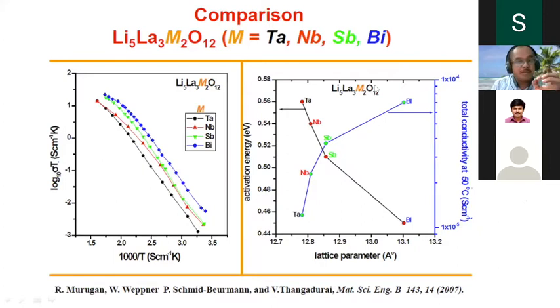When I substituted tantalum, niobium, antimony, and bismuth, you can see the best conductivity I got was for bismuth, next to antimony, then niobium and tantalum. Then I realized some correlation between this conductivity and this substitution. When I looked into the lattice parameters, moving towards bismuth, you can see the activation energy goes down from tantalum to bismuth, because bismuth has the maximum conductivity in this series. But the lattice parameter increases. It's a cubic structure. When I was able to expand the lattice, conductivity goes up and activation energy comes down.